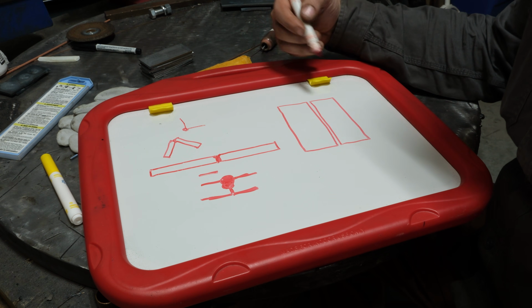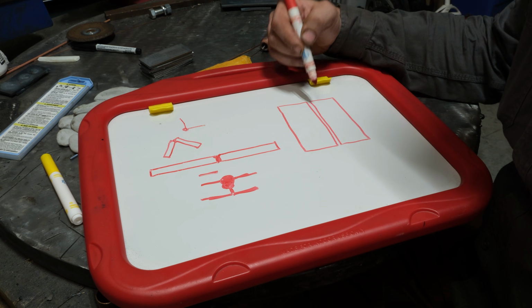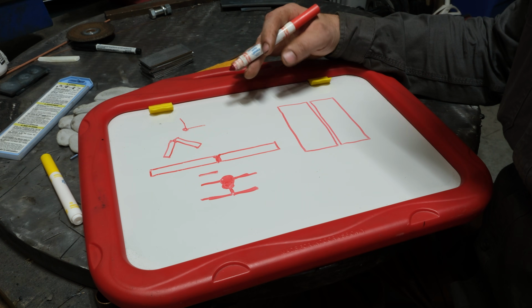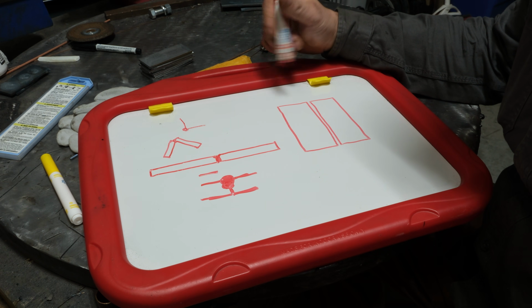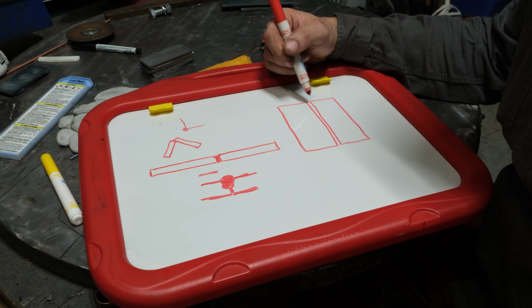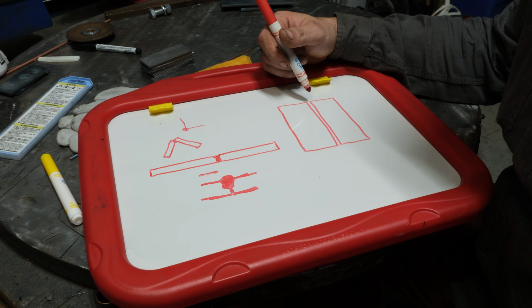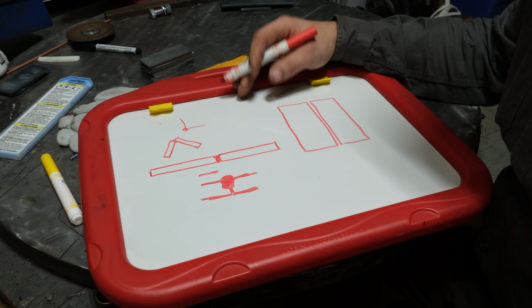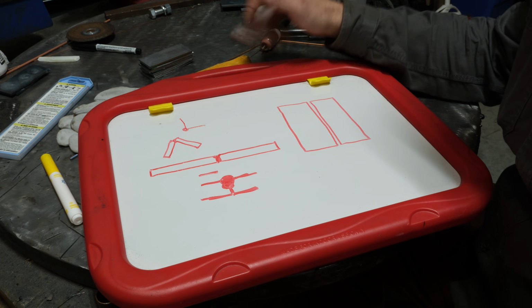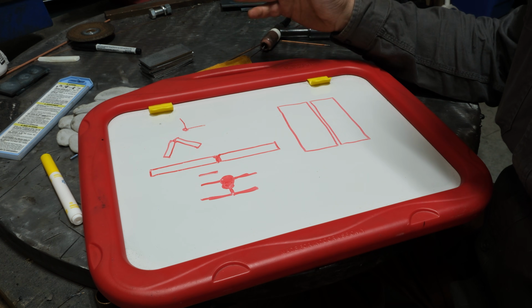Now again, the setup should be take your two plates, no gap, and because this is roughly 3.2 or 1/8 inch material, we're going to run at about 120 amps. And that should be the ballpark of what you're looking at. So what I'm going to do is get set up, and we're going to start welding. We're going to watch this in real time, one time with me commenting and one without.